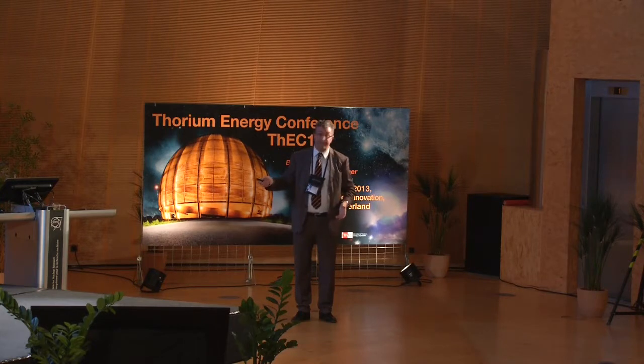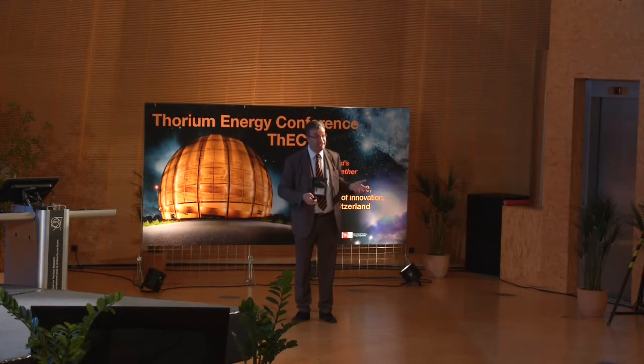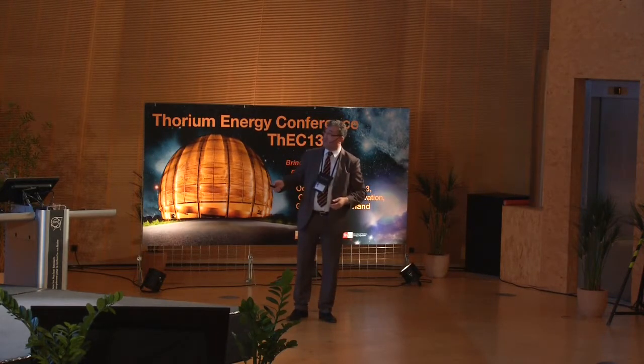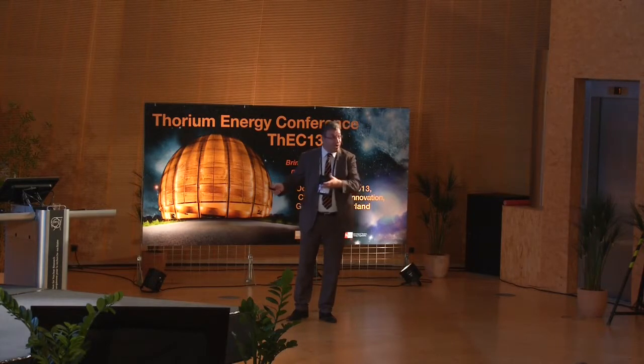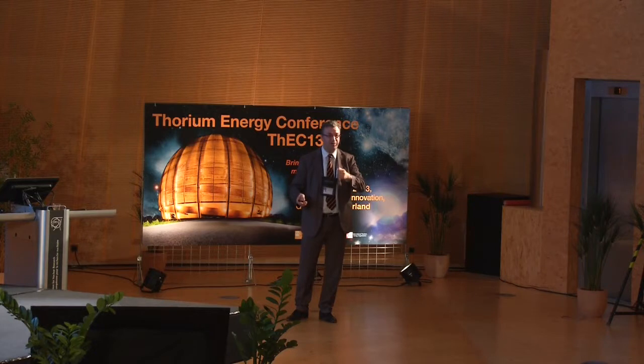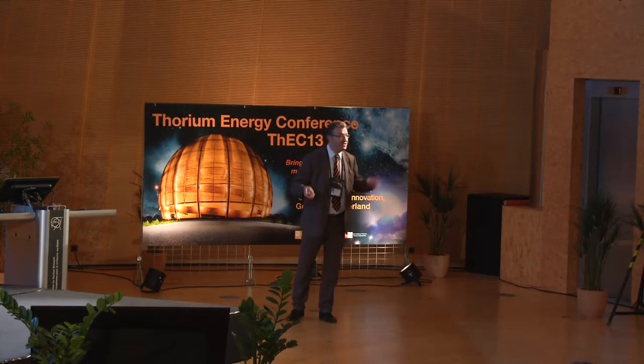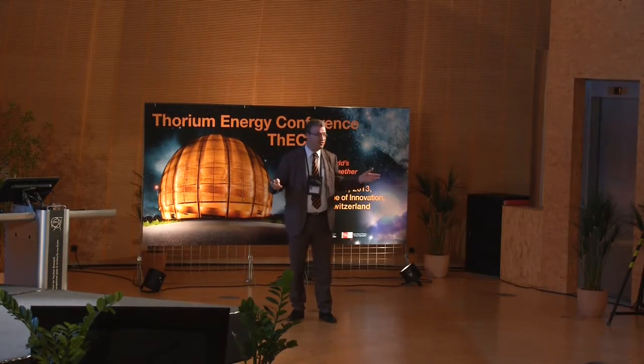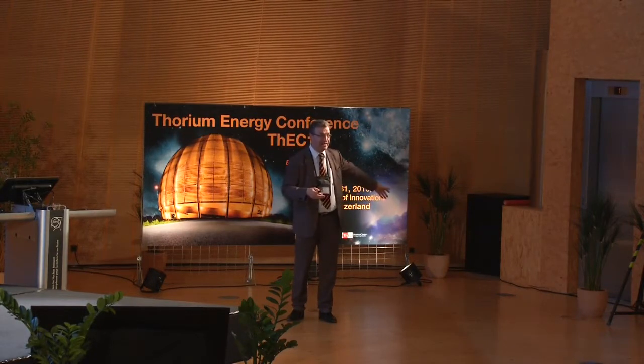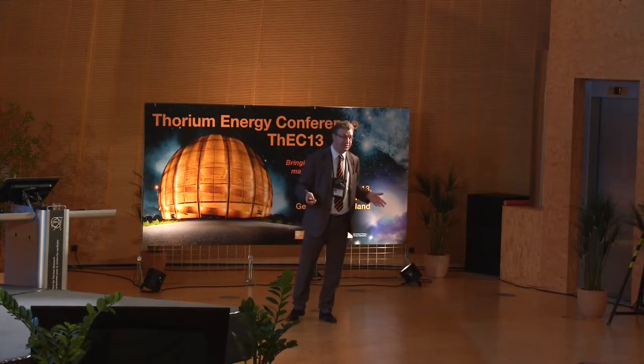But now, ITU has upgraded its facility to 200 kilograms of minor actinide and plutonium. So in Europe we now have something that allows us to do things. The third block is these dedicated burners, and one of them is MYRRHA. But not to forget the advanced fuel containing a large amount of minor actinide, we need specific reprocessing. And I think pyro reprocessing or whatever is the way that we have to go. We can't treat that with our classical water reprocessing. If you have to wait 10 years before you can handle it, to burn 1 core takes you 100 years. This is not acceptable.